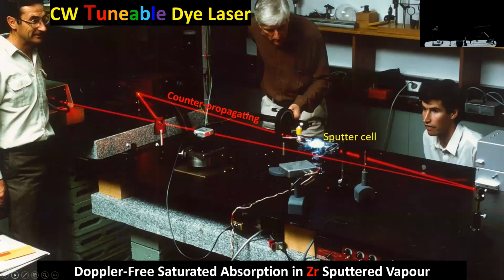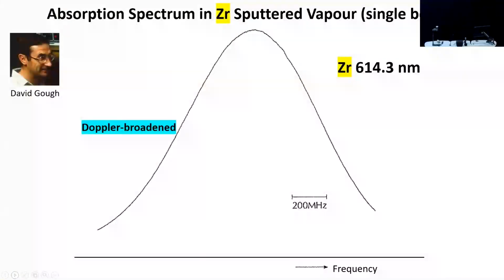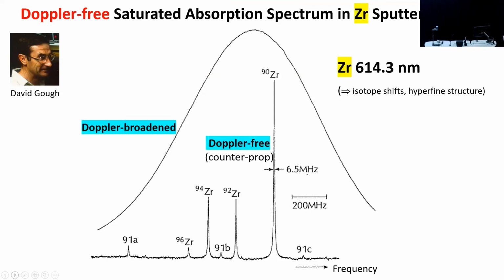Again, we chose zirconium, and this shows if you use just a single beam, the absorption spectrum, which is the Doppler broadened spectrum. It's still very narrow, it's only about 1 gigahertz or less. And now when you use 2 beams, counter-propagating arrangement, you can see the full isotopic structure and the hyperfine structure. With the different isotopes here, this depends on the mass of the isotope and on the charge distribution of the nucleus in that particular isotope. While the 91 being an odd isotope, you can see the hyperfine splitting here.